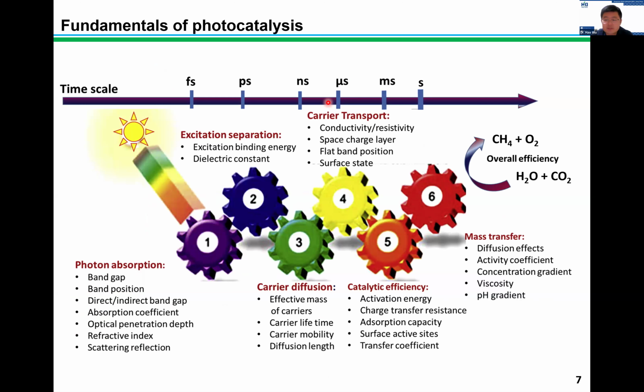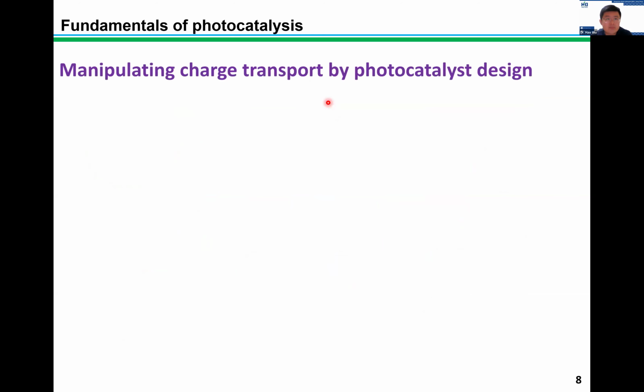But those properties relevant to the charge transport are the effective mass of carriers, carrier lifetime, carrier mobility, and diffusion length. Also, the conductivity and the resistivity of the semiconductor, the width of the space charge layer, and also the position of the flat band or the surface states, with shallow or deep surface states. Upon knowing the properties that we can regulate for semiconductors, I would like to introduce the general strategies for manipulating charge transport by photocatalyst design.